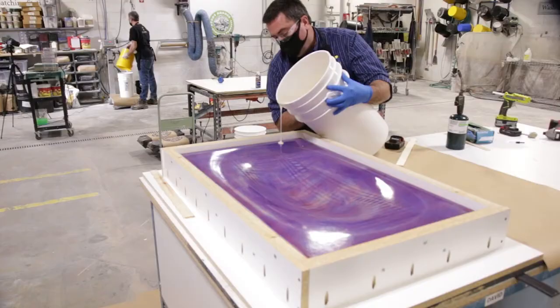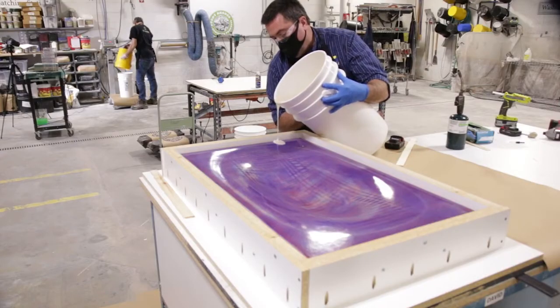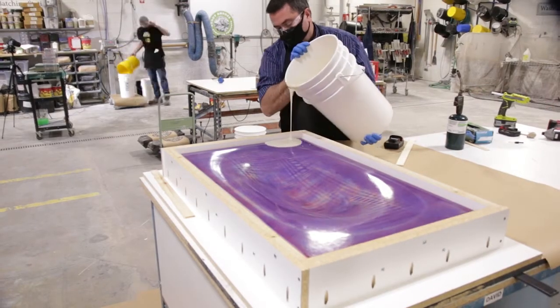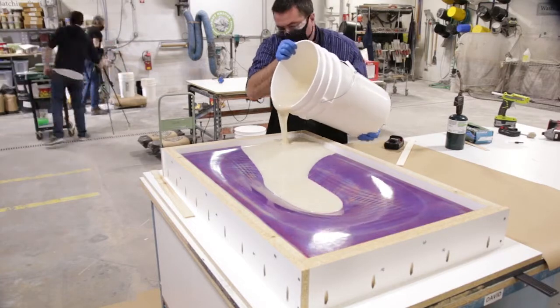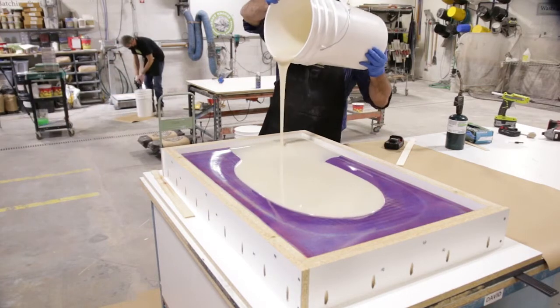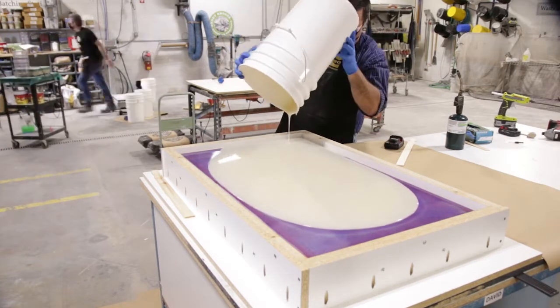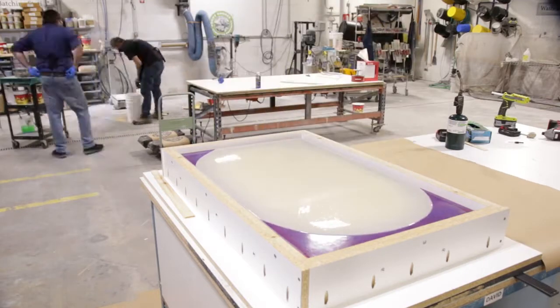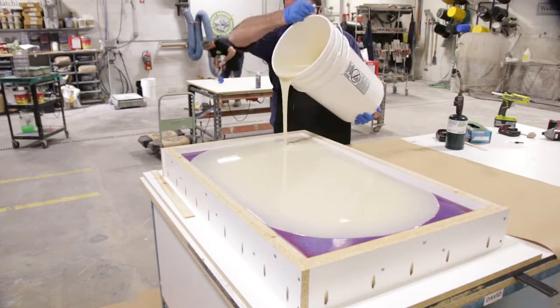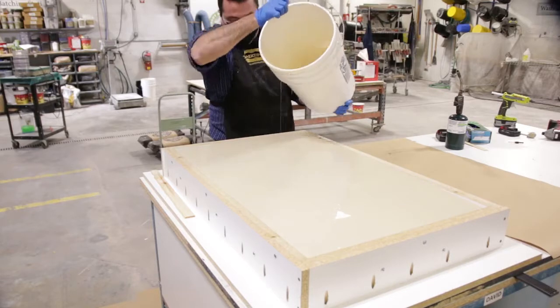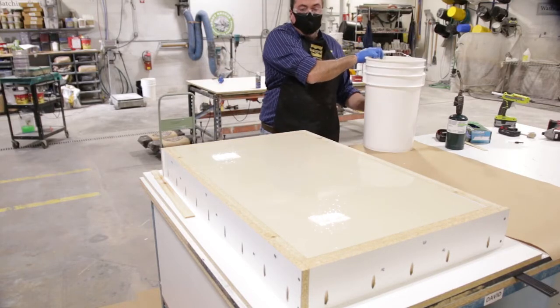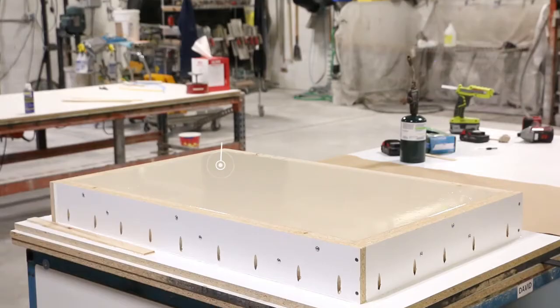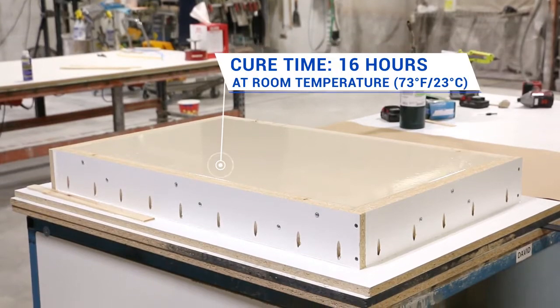Begin pouring the mixed rubber into one corner of the mold box. Once the mold rubber has come over the top, continue to pour into itself, keeping the stream behind the lead edge of the flow. Continue to fill the mold box until the appropriate thickness across the back of the mold has been reached. Inspect for possible leaks and allow to cure for 16 hours.